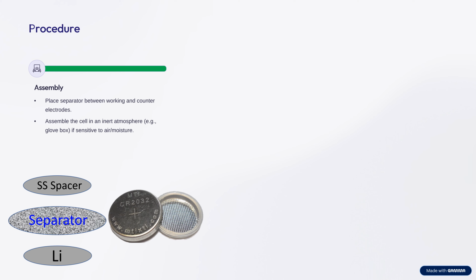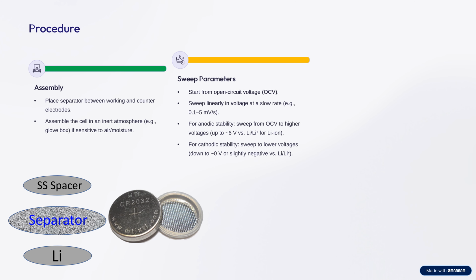And you should do it in a glove box if it's a lithium or sodium ion battery. And then after assembling and crimping the cell, you have to start the test. Basically, you have to apply the voltage sweep within a certain range and at a specific rate like millivolt per second. For anodic stability, you can scan from 2 to 5 or 6, and for cathodic stability you can scan down to 0. But here we will focus only on anodic stability because most of the batteries use from 2-3 volt to 4 or 4.5 volt.